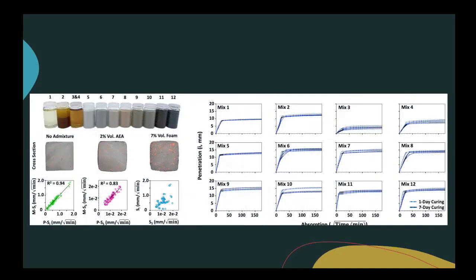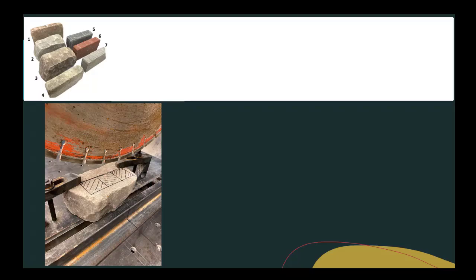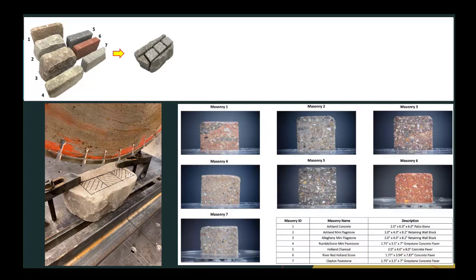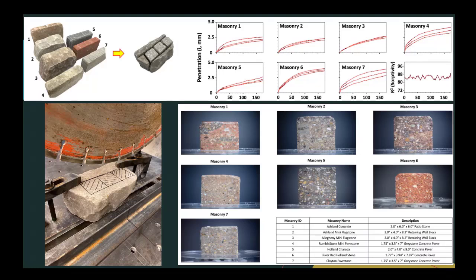And apart from that, I also used cement paste mixed with different SCMs, clays, fly ashes, slags, even foam concrete. So this was the foam solution. And then even on masonry elements. So I cut this sample to 2 inch cubes. So these are the samples. And then I tested 7 commercially available masonry units, everything I could buy from Home Depot, and then it worked. So I was able to predict that. So it works on paste, mortar, concrete, and masonry.